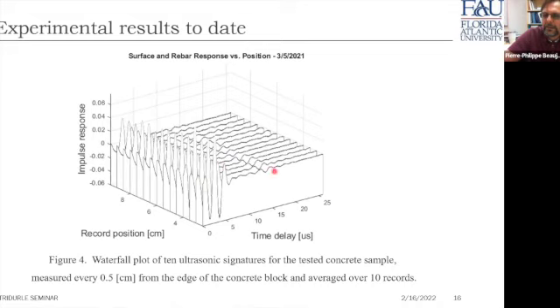This over here, after about 10 microseconds, is going to be the echo from the concrete block. And right here, this faint echo after about 17 microseconds is the reflection of the rebar. So again, the transmitted impulse is the first one at 0 microsecond. The surface echo is going to be at 10 microseconds, and the rebar echo is going to be at approximately 17 microseconds.